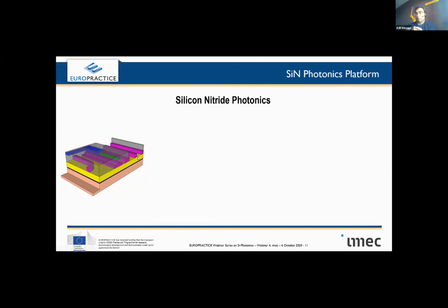The question is, what are the ways to deposit silicon nitride? There are basically methods. You can use different kinds of CVD methods, depending on what kind of operations or what kind of device you want to make. And with silicon nitride, there is more freedom to deposit things. In contrast to silicon photonics, where usually the waveguiding layer, which in this case is silicon, used to be typically crystalline. So it's not so easy to deposit crystalline material. Maybe polycrystalline material, but not crystalline material. So silicon photonics processing usually starts on SOI wafers, or silicon on insulators, while on silicon nitride, just a deposition of silicon nitride would be enough.